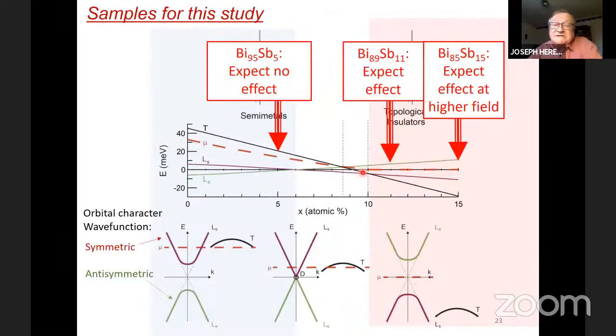So we're going to measure three samples at 89.11, which is right here in the topological insulator Weyl point regime, a sample at 15%, which should give the same answer, and then a sample at 5%, which has T-holes. So this is a system with trivial pockets in its Fermi surface, and that's where we do not expect effects, whereas these we can get to the situation where we have ideal Weyl points. So this is the null experiment, if you wish.